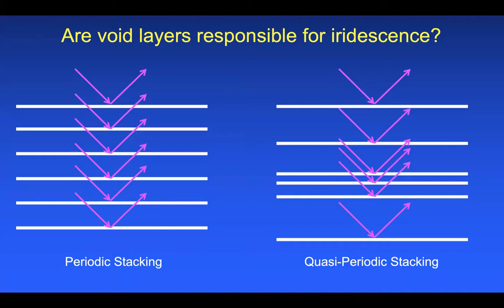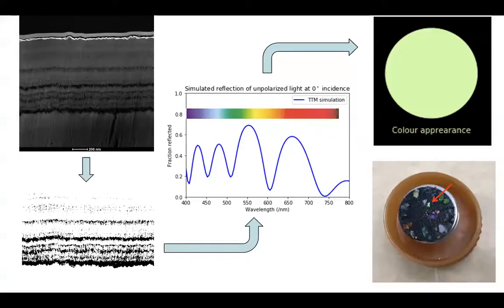But when we're dealing with this tergite, it's the same color no matter how you tilt the tergite. And that is often consistent with a quasi-periodic stacking sequence that destroys that angle dependence. So I then collaborated with Tobias Wenzel. At the time, he was a postdoc at the University of Oxford, and he specializes in these quasi-periodic interference effects.